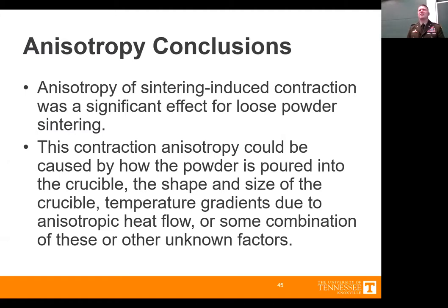As far as the cause of the anisotropy, it's still unclear what all factors go into that. The problem with sintering theory is there are literally so many variables that apply and could have a significant impact on that green body. And so if it's not exactly the same from trial to trial, you get some kind of random errors thrown in there. But even if those green body processes are the same from trial to trial, something is causing, if you subscribe to the Hans Eckert theory of pore elongation, the pores in that loose powder to be preferentially elongated in the axial direction. And it's unclear, at least for my work, what those factors are. This is just some of the factors that could be a cause.